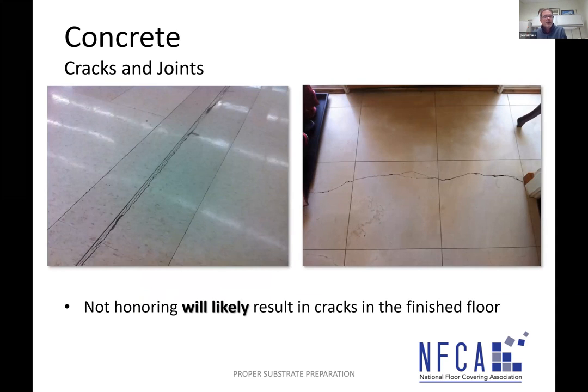Couple of pictures here. On the left, that's VCT installed over an expansion joint. And you can see that they installed another row because the dye lots are different, and it cracked the tile. On the right, you've got a crack moving in the concrete that has cracked the hard tile as well. If we don't honor them or repair them, they show through.